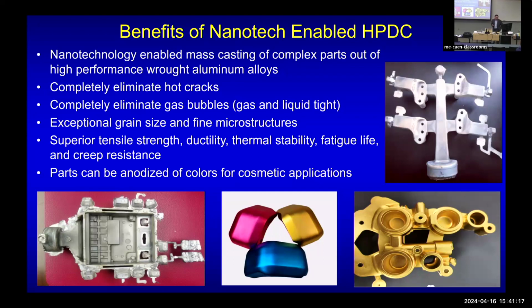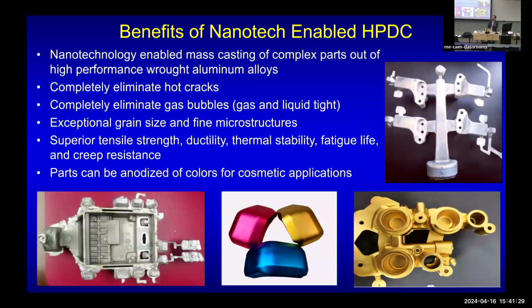And also superior grain size and fine microstructure and properties: tensile, ductility, thermal stability. Surprisingly, the fatigue life, we get enhanced a lot. That's one thing 10 years ago we did not believe. Nobody believed it. Most people think, oh, you put a nanoparticle, a heterogeneous particle, in, you will reduce fatigue life. But actually, in recent years, we found that we enhance fatigue significantly. It's because nanoparticles block the crack initiation, and also block the penetration. Right? So that's a surprising effect.